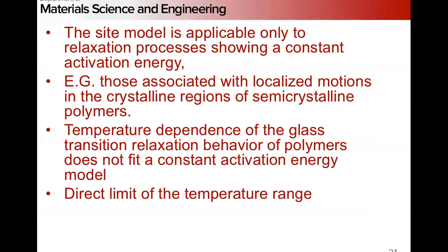An example of where this breaks down would be localized motion in the crystalline regions of semicrystalline polymers. So this nodal site theory doesn't work. And the temperature dependence of glass transition relaxation in polymers does not always fit a constant activation energy. So that's a direct limit to the range that we can use. We cannot use this to compare responses from well below the glass transition to well above the glass transition.